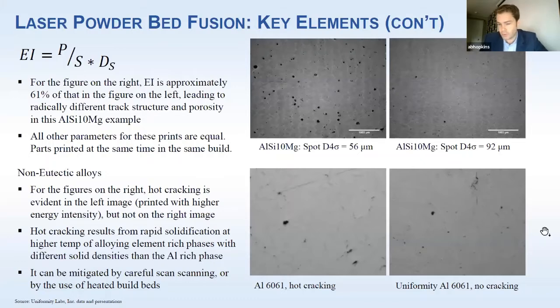So there are things you can do with both the processing parameters and the alloys themselves and the powder to address some of these problems with non-eutectic alloys, for example, in aluminum. There's a company out there that adds zirconium hydride or something similar to their mix, and the zirconium prevents the formation of these hot cracks by creating these very fine grains. You do get something that has low elongation to failure. It's more brittle, but you get rid of the hot cracks. So there are some applications for that kind of thing.